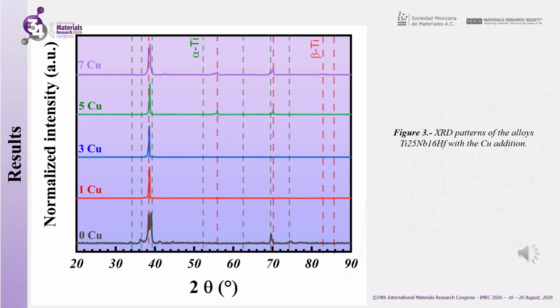As illustrated in Figure 3, the X-ray diffraction patterns obtained for the analyzed alloys are presented. The absence of added copper results in the presence of alpha titanium and predominantly beta titanium phases. For the alloys containing copper at 1 to 7% by weight, the alloys predominantly exhibit the beta phase of titanium with a body-centered cubic structure, suggesting that copper dissolves in the titanium matrix, without producing new phases detectable by X-ray diffraction, thereby completely establishing the beta titanium phase as the concentration of the copper addition increases.